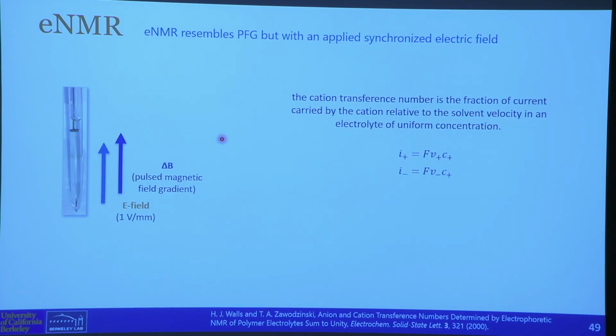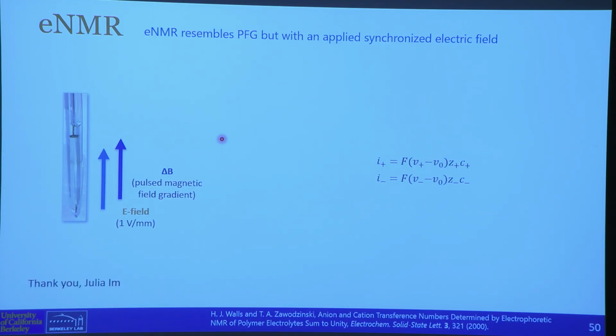We all know that current is Faraday's constant times velocity times concentration. The problem is that you need a reference frame any time you measure velocity. It's especially true if you're driving a Tesla, right? You don't want to stand on the road and measure the ion velocity. So there has to be some reference frame, and the gurus of the field chose the solvent as the reference frame. The reason the solvent has been ignored is because everybody has been sitting on the molecule and saying it doesn't move. It's actually almost like that, not quite that bad.